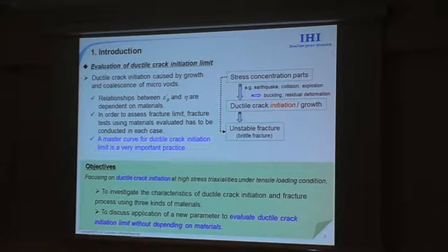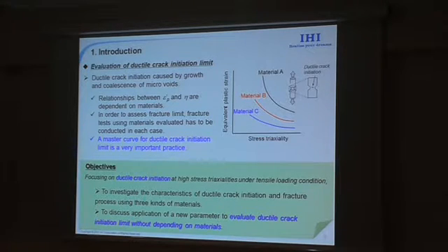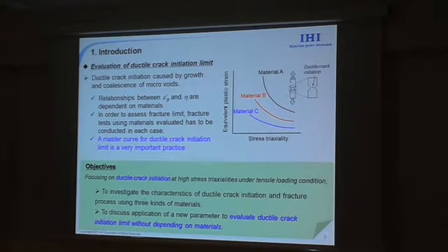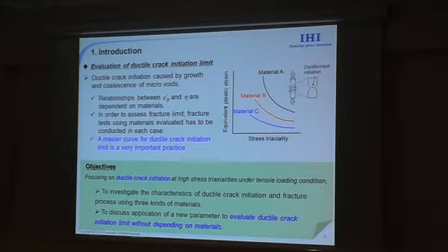As for evaluation of ductile crack initiation, the relationships between equivalent plastic strain and triaxiality have been used and are dependent on materials. Therefore, in order to assess fracture initiation, we have to conduct fracture tests in each case to obtain these relationships. So, if we can get a master curve for ductile crack initiation, it is considered to be very important in practice.